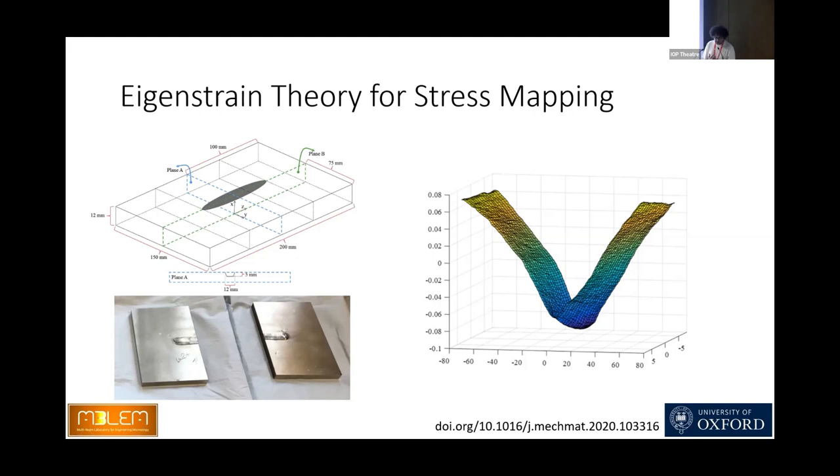Measuring the elastic response due to stress relaxation in terms of displacements using extensometry techniques, which can be contact or optical extensometry, allows the determination of eigenstrains.